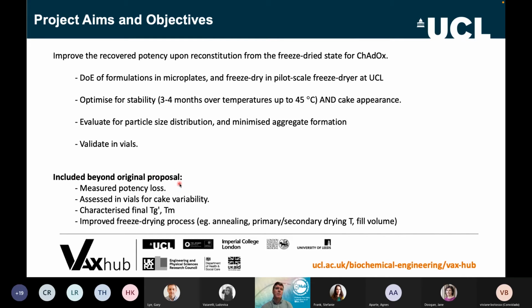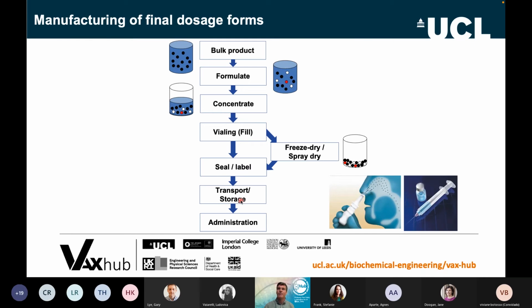And actually we went a long way beyond those objectives, because once it looked successful, then we started to look at measuring potency loss. That was done in Oxford, assessing in vials for the variability, characterizing the freeze-dried materials in terms of the melting and glass transition, and generally put in a lot of work to improve the freeze-drying process as well, which I'll discuss as we go through.